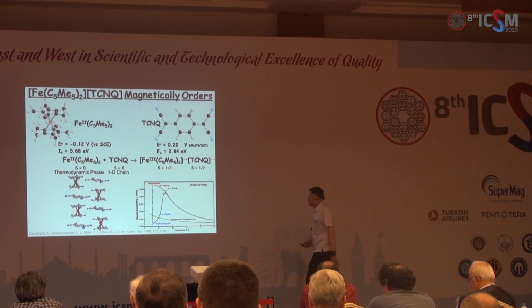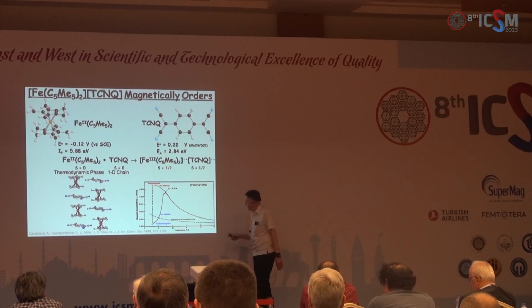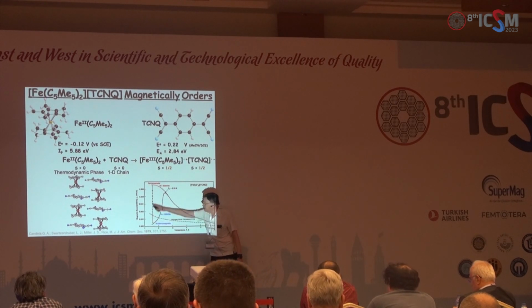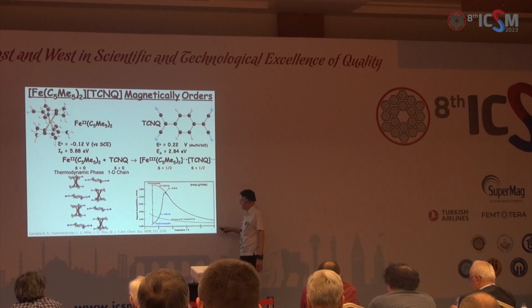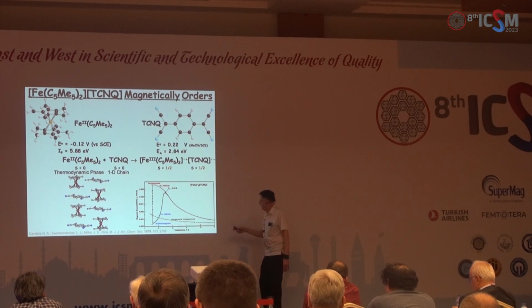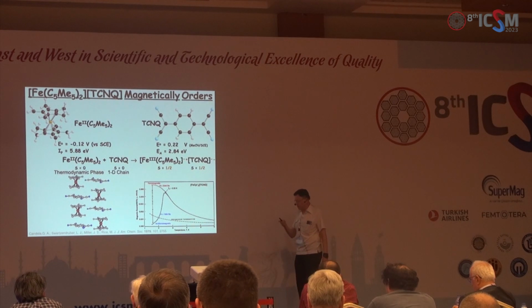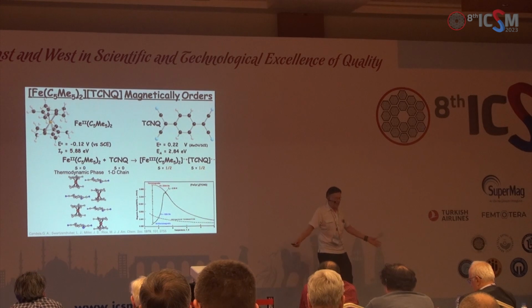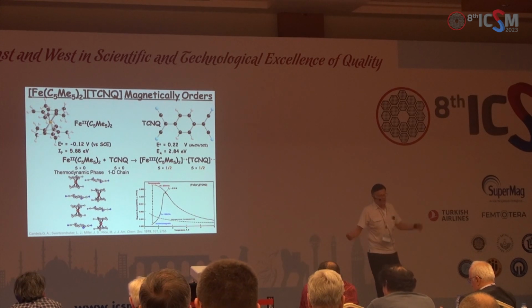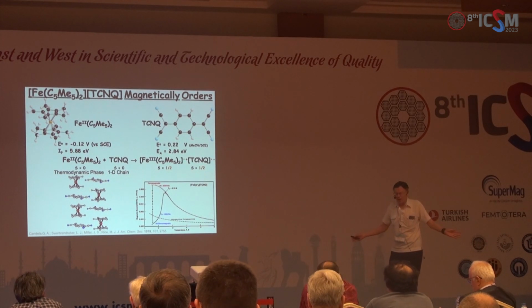It's a little hard to see, and I apologize, but on the y-axis is magnetization, and the x-axis is Kelvin, 1 to 6 Kelvin. And when you look at the magnetic susceptibility, as you measure it at 1,000 Gauss applied field, it goes up, reaches a maximum, drops down. That's an indication of antiferromagnetic behavior, and not particularly a surprise.